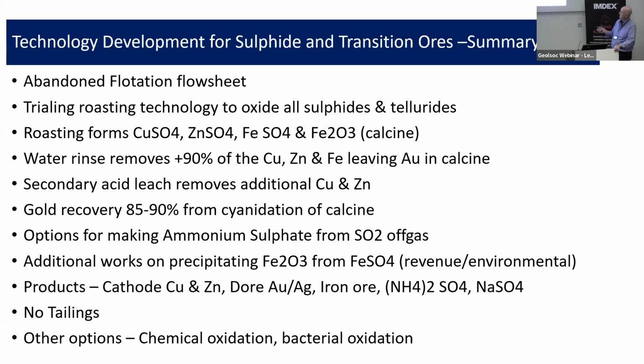If you just water rinse it after roasting, you can get over 90% of the base metals, leaving the gold and silver in the calcine. So we're continuing this process. It's not completed yet, but if we'd have known this early on, there was probably $5 to $6 million worth of test work that would not have been necessary if they'd have understood the ramifications for mineralogy.